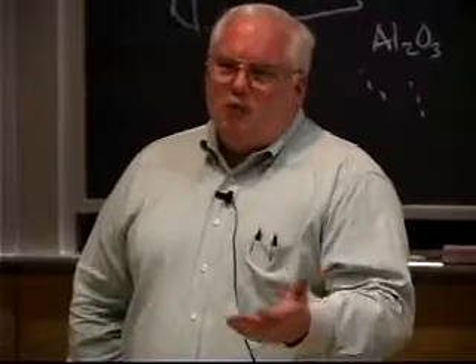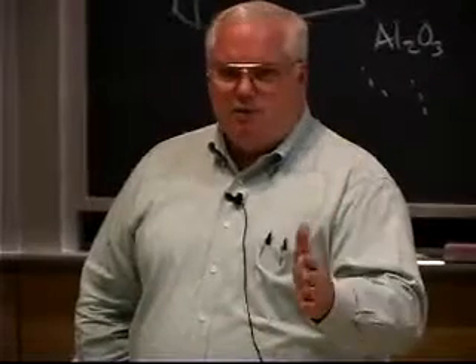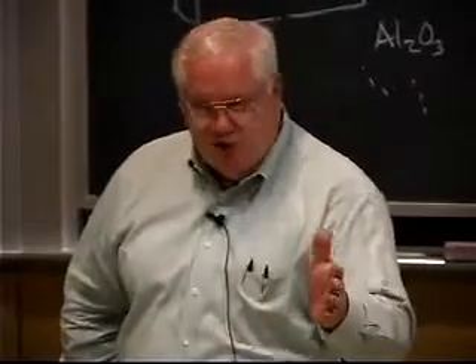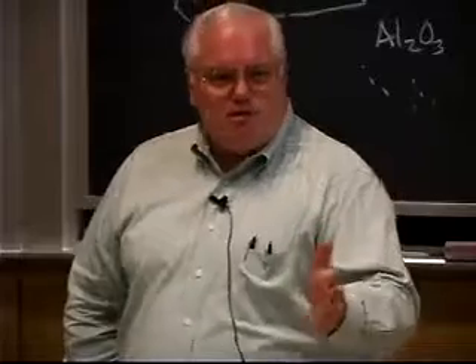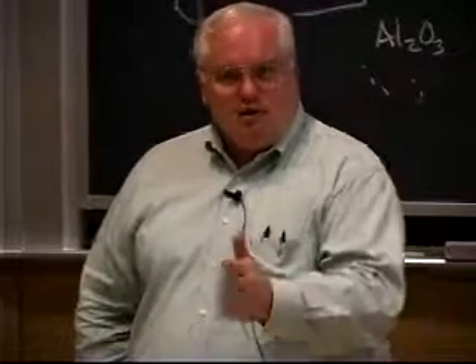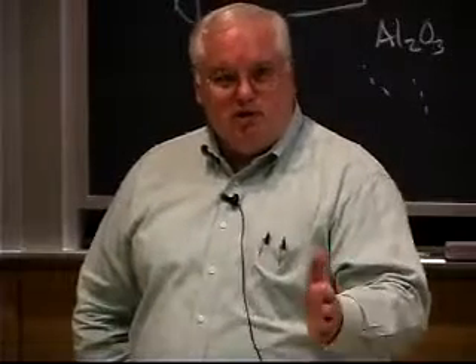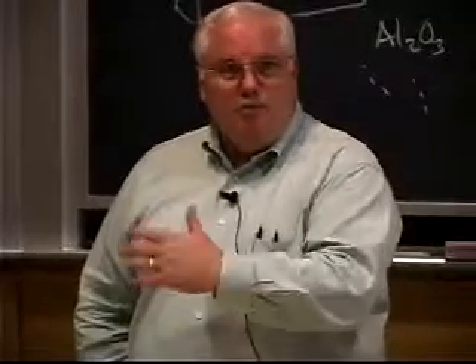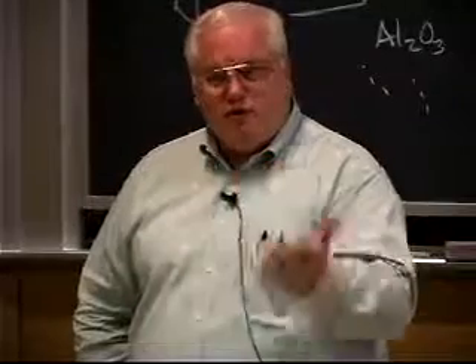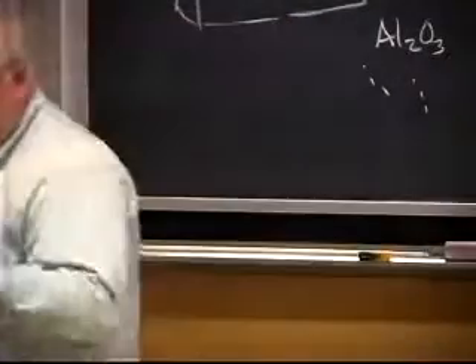And the problem was, sometimes they were getting 30% bonded area, and sometimes they were getting 10% bonded area, and 10 wasn't good enough. 30 was, but 10 wasn't good enough. But 50 or 70 would probably be worse again for that particular application, because you needed a pattern interlayer. Okay? Any questions on any of that?